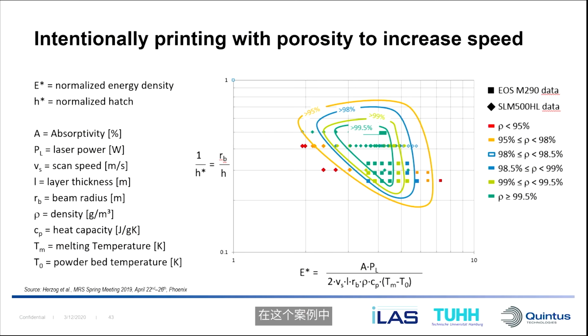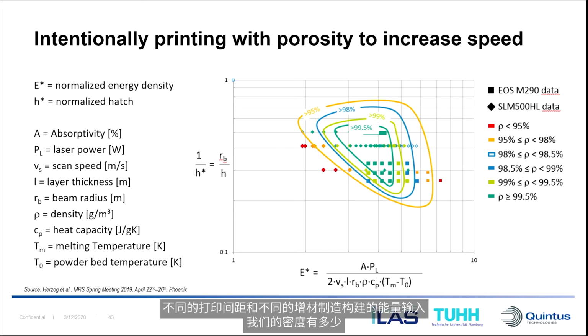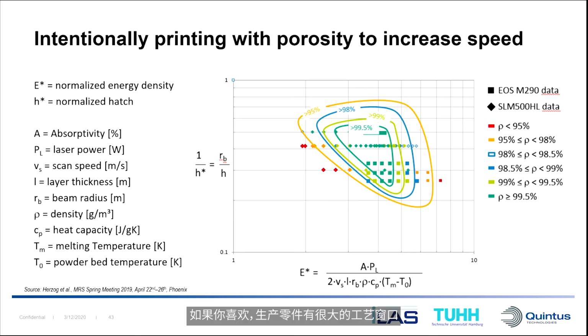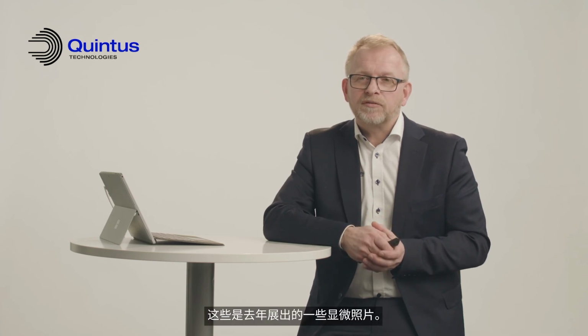In this particular case, University of Hamburg, Technical University of Hamburg, and Dr. Dirk Herzog have done some work looking at, okay, what happens if we print quicker? What kind of density do we get in this material, titanium 6.4, with varying hatch distance and also energy input into the additive manufactured build. And a lot of work's been done on this, and they've identified some areas now where down to 95% density can be achieved, but with a much bigger process window, if you like, for production of the parts.